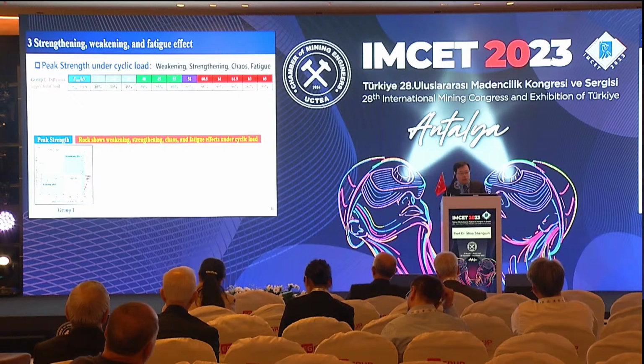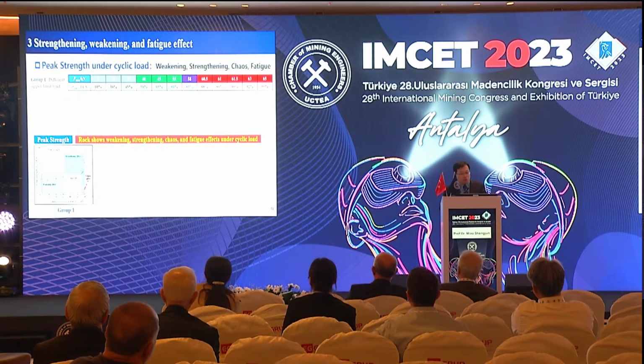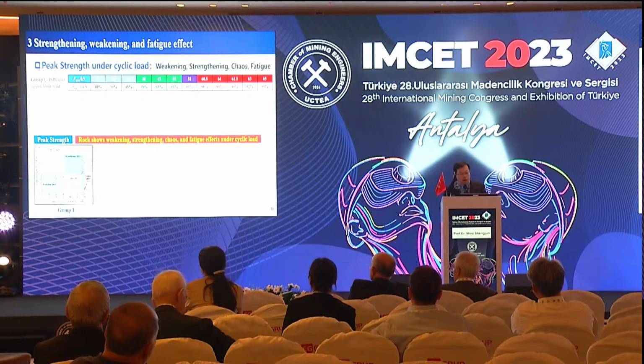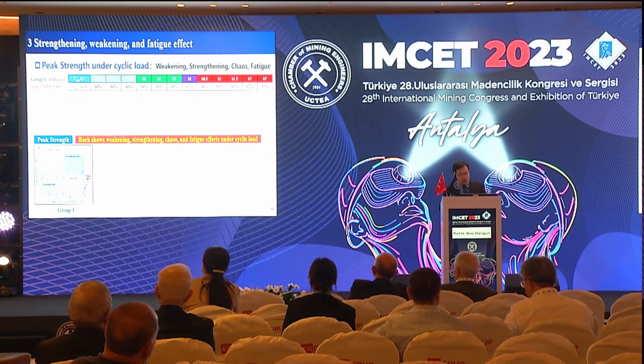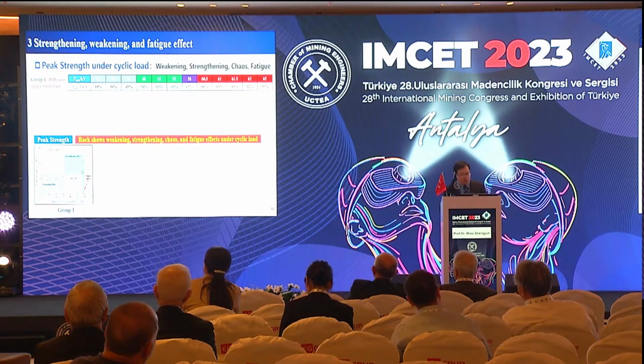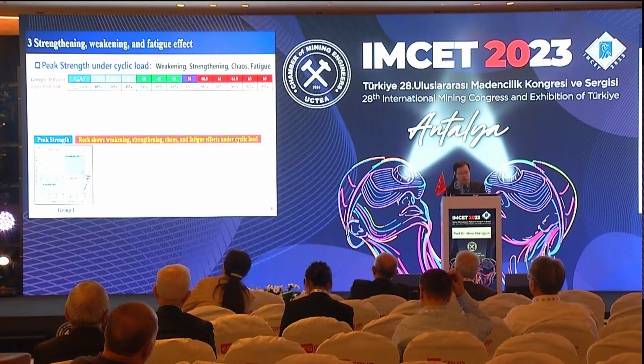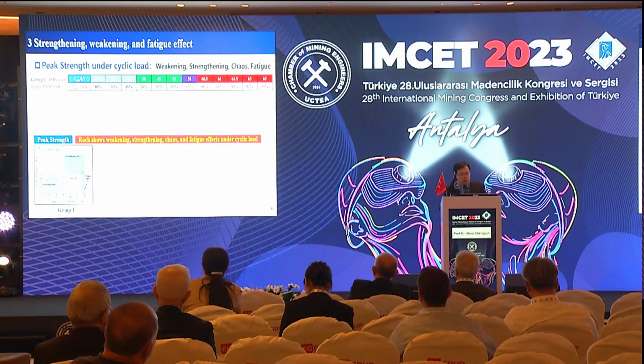Firstly, based on the cyclic loading test on siltstone at different upper limit loads, we found that the peak strength of siltstone showed the weakening, strengthening, and fatigue effect with the increase of the upper limit load. Specifically, when the upper limit load is in the initial compacting stage, the siltstone peak strength is lower than the UCS. When the upper limit load is in the elastic deformation stage, the siltstone's peak strength is higher than the UCS. The siltstone's fatigue strength is about 88% of the UCS.